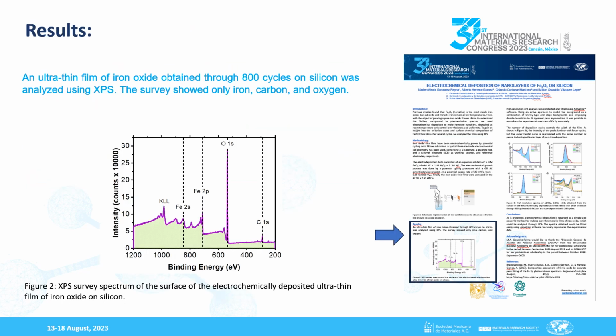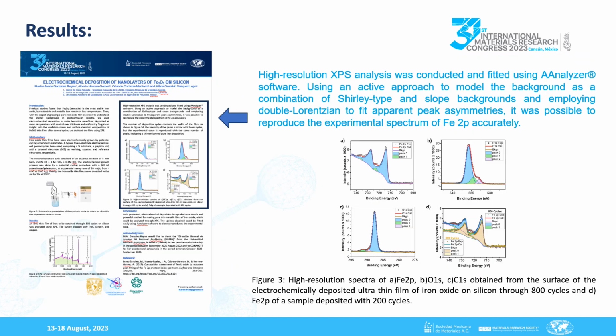To gain an insight into the oxidation states and surface chemical composition after 800 cycles, XPS measurements were carried out. Figure 2 shows the survey spectrum showing only iron, carbon, and oxygen in the film, suggesting a pure oxide deposition. To corroborate this hypothesis, high-resolution XPS analysis was conducted and fitted using AAnalyzer® software.